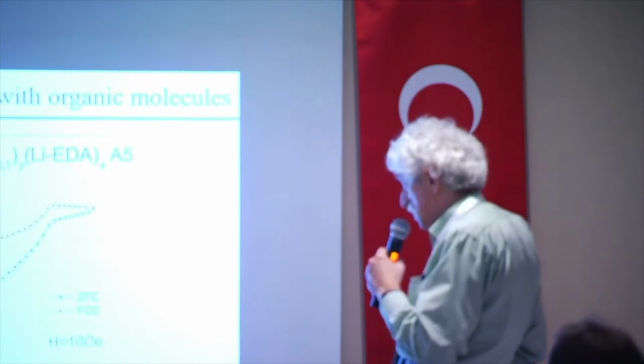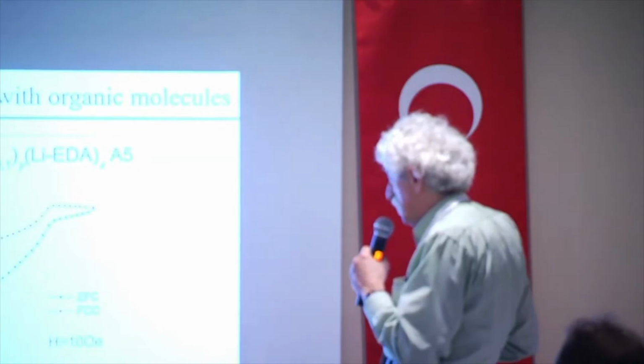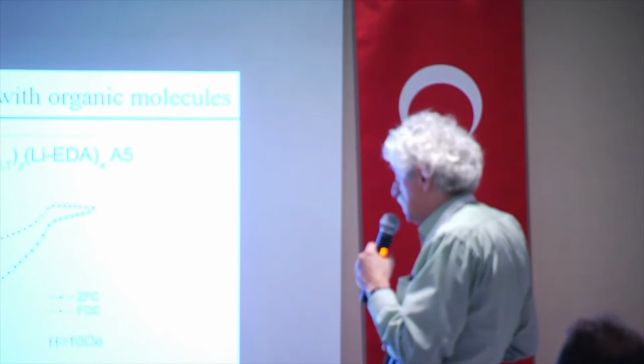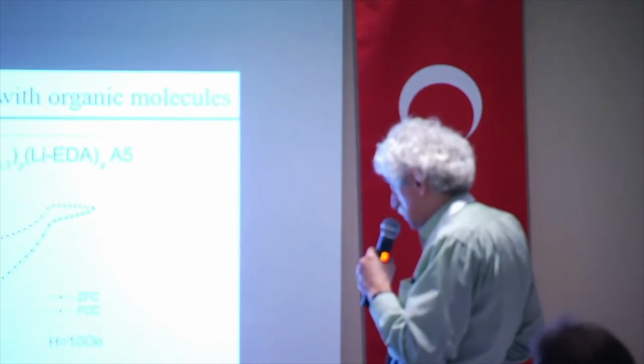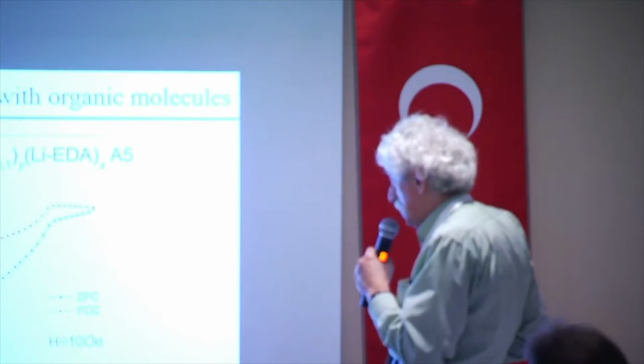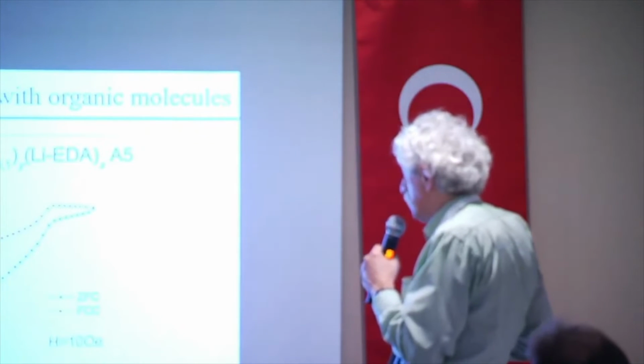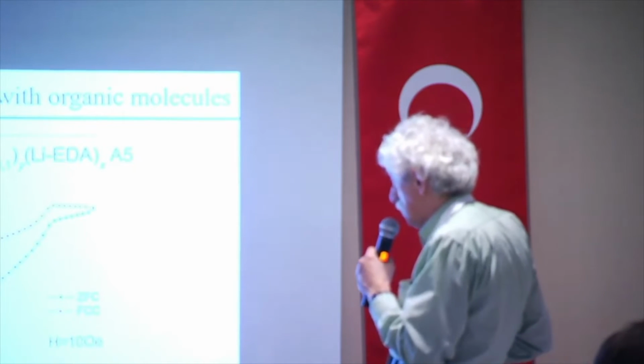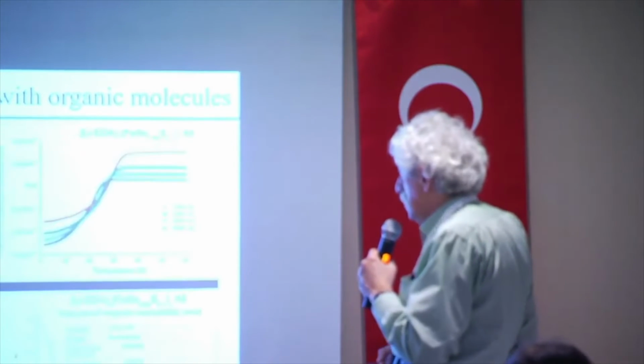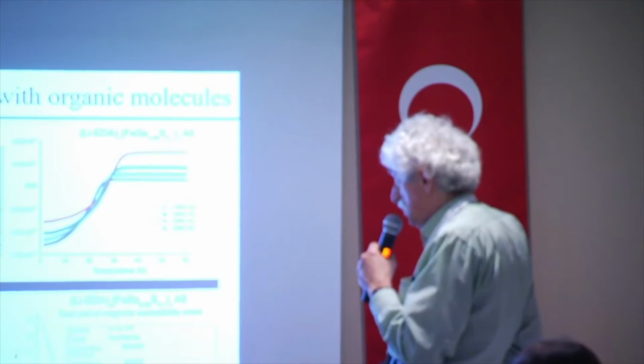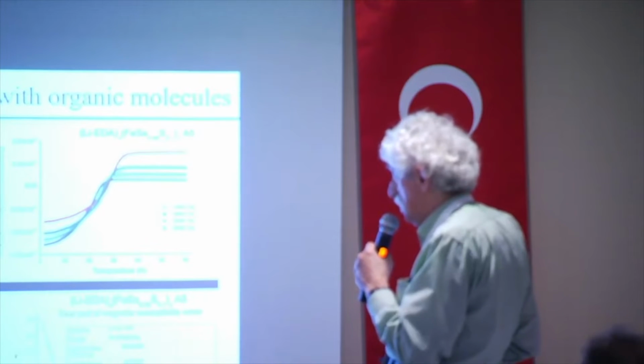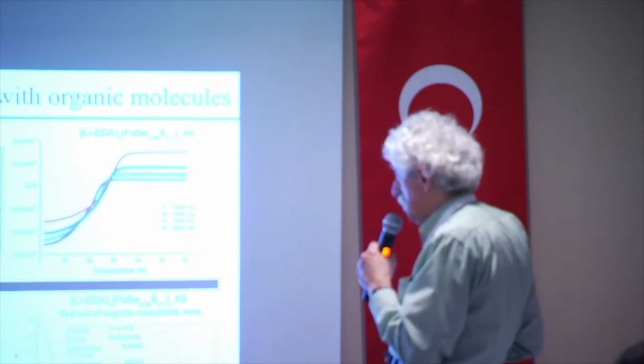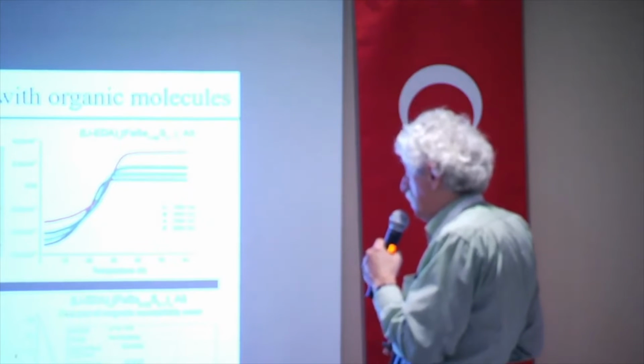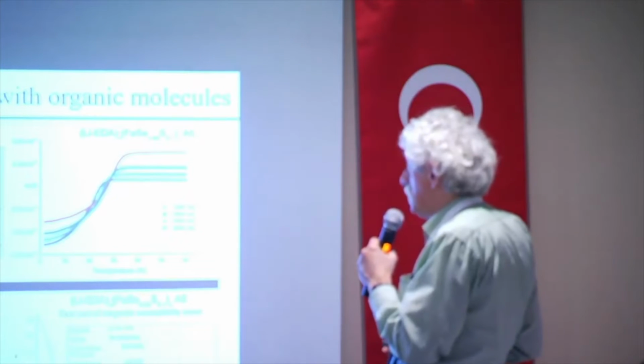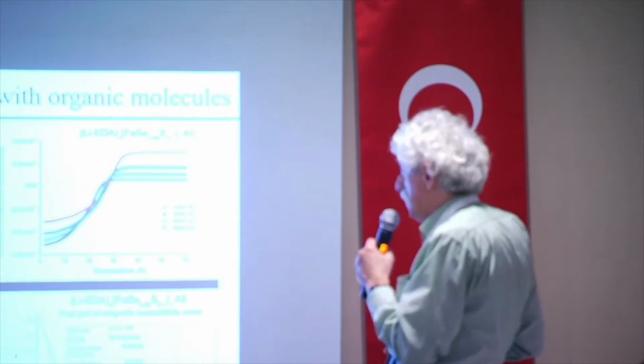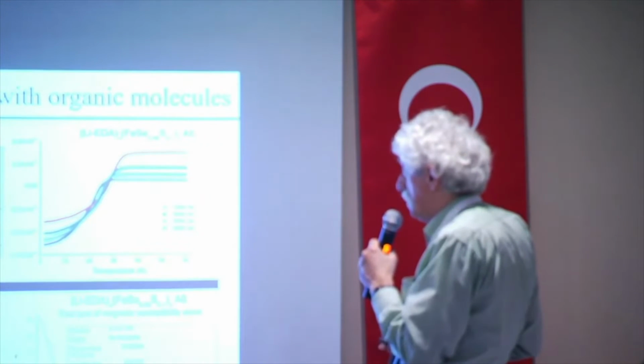However, you must know that the superconducting properties of this material are also not ideal, and you can have in such materials some ferromagnetic impurity or something like this. So you can see, for example, this is zero field cooled magnetization. Of course, there is a transition at about 40 Kelvin, a nice transition, but still you have some background signal. And we decided to measure HC2 for this material. The HC2 measurements were done in this way: the sample was warmed in a constant magnetic field, and the appearance of a constant signal, which is temperature independent, was considered as the upper critical field.